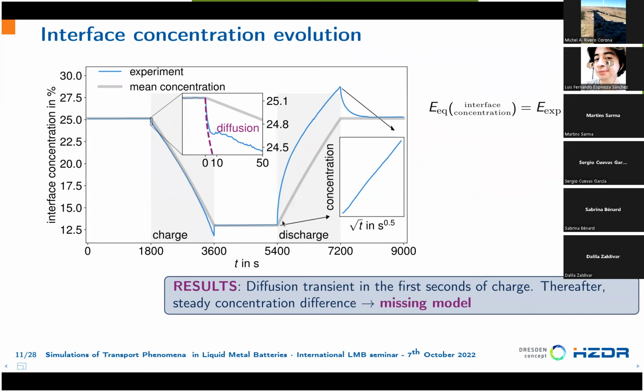Instead, during discharge, we have a very large concentration difference with respect to the mean, that is the gray line. So the blue is the experiment, the interface, and the gray is the mean. And if we compare with the square root of time scaling that we were expecting for the interface concentration, we see that, yes, this lies perfectly on a line.